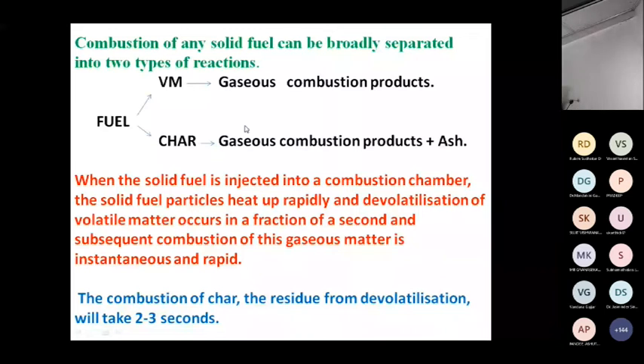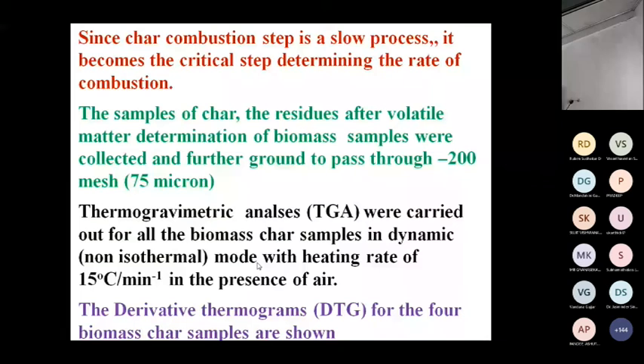So combustion of any solid fuel can broadly be separated into two types of reactions. Fuel is converted to VM and char. VM leads to gaseous combustion products. Char leads to gaseous combustion products plus ash. When the solid fuel is injected into the combustion chamber, it first heats up rapidly and devolatilization of volatile matter occurs in a fraction of a second, and subsequent combustion of this gaseous matter is instantaneous and rapid. The last activity is combustion of char. It will take 2 to 3 seconds. Since char combustion is a slow process, it becomes a critical step in determining the rate of combustion. So the rate of combustion is decided by the slow process.